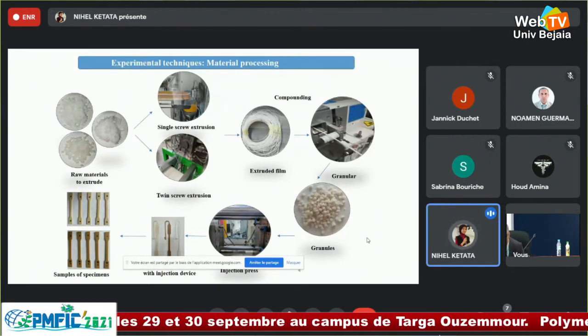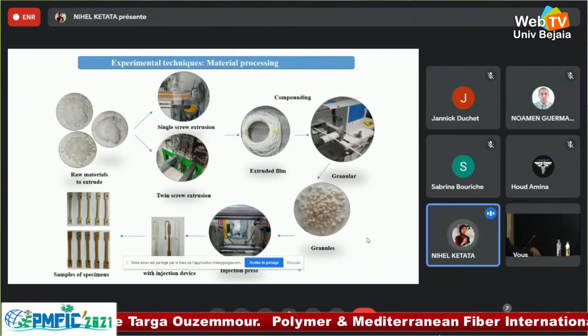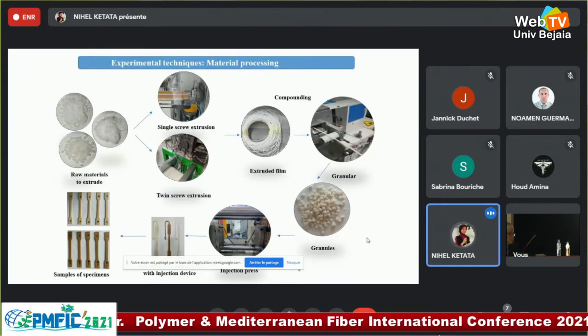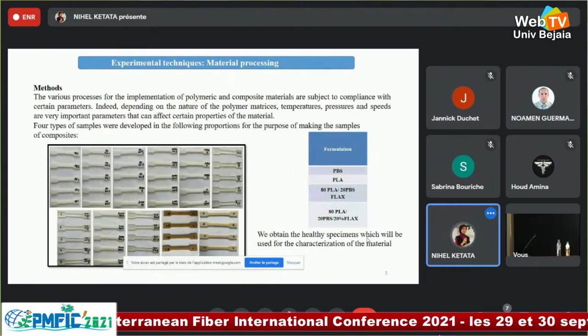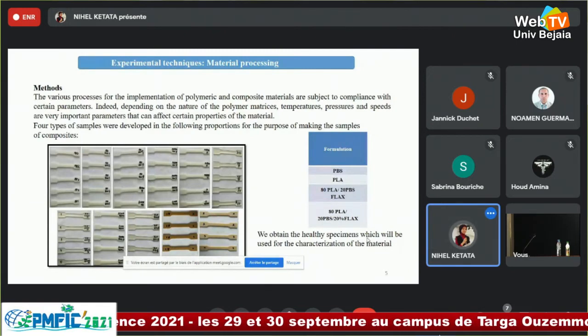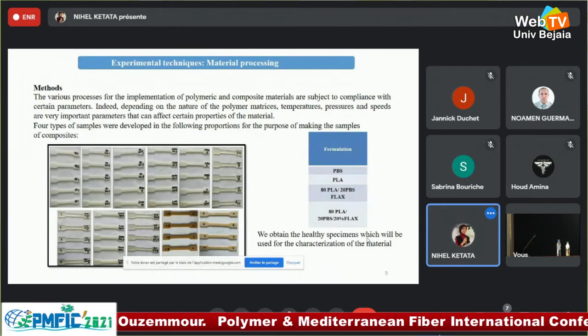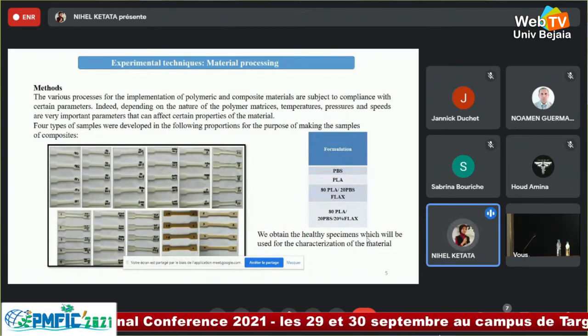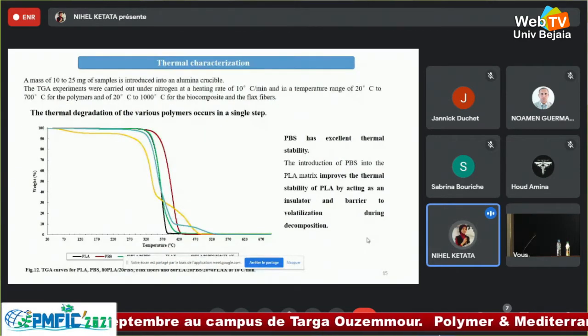So we use the single screw and the twin screw extrusion methods to obtain the extruded films. Then we granulate them to inject the test specimens and finally obtain the dog-bone specimens which will be used for the characterization of the material. We made four types of formulation: the PBS version, the PLA version, 80% PLA with 20% PBS for the matrix, and 80% PLA with 20% PBS reinforced with 20% of flax fibers.